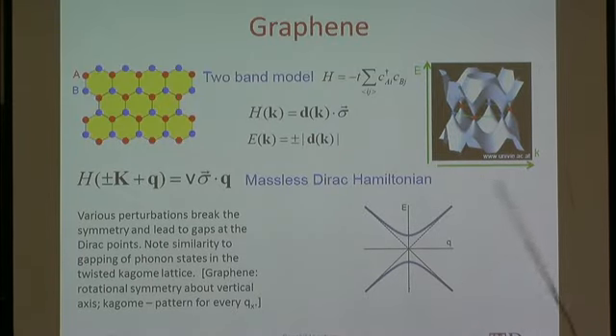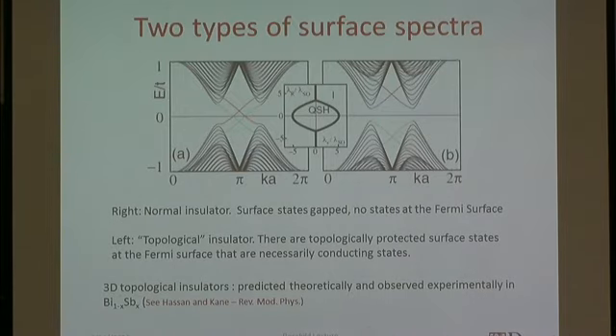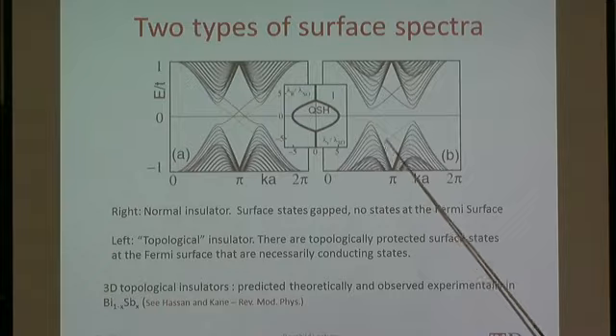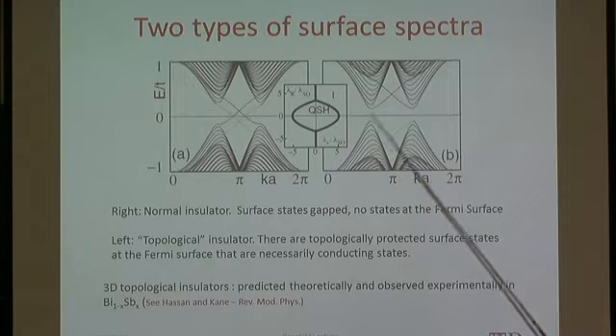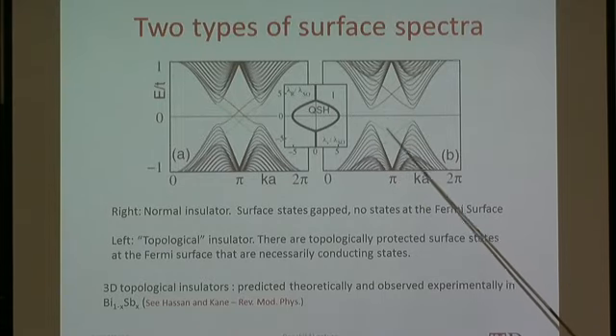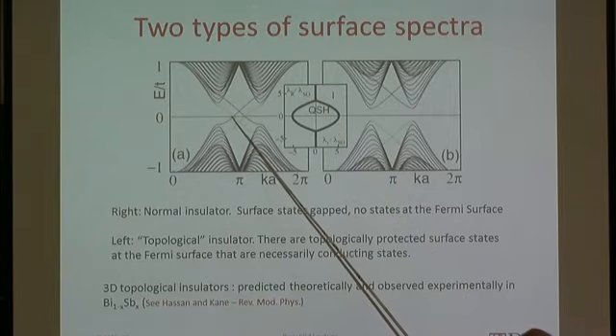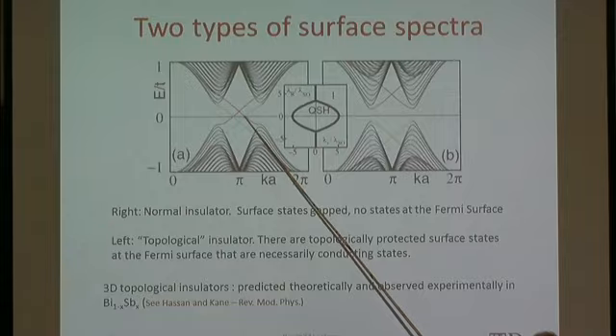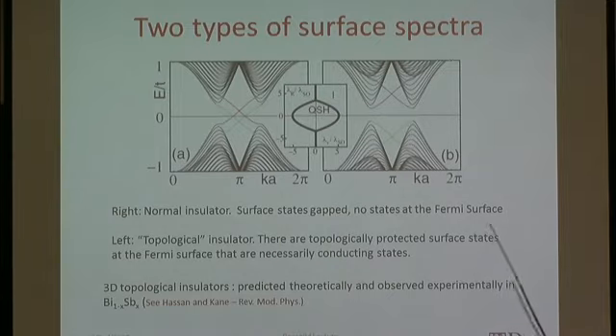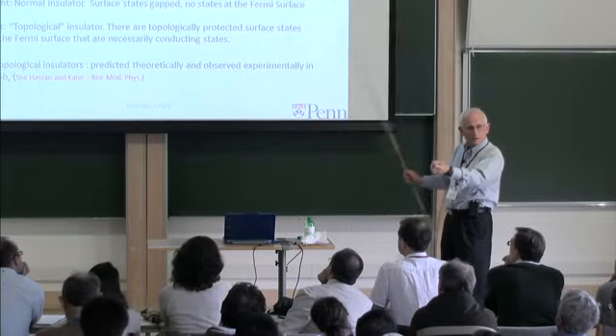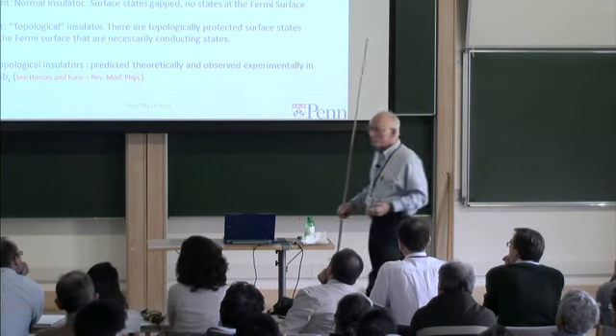And then the question is, do these gap states have different topological characterizations? And the answer is yes. And there's basically, you either have a plus state or a 0 state. In the standard insulator, here are the bands with the gap. Here are the surface modes that look like this. Here is the standard insulator where the Fermi surface sits in a region where there are no surface states. Here, the Fermi surface crosses the 0 modes, the surface modes, and therefore these states right here are conducting. Right? So you can have an insulator that conducts on the surface. And there's a lot of very interesting physics, which I don't have time to go into, and I don't really have totally digested myself, about the spins, which allow these things to be protected even when you turn on interactions.